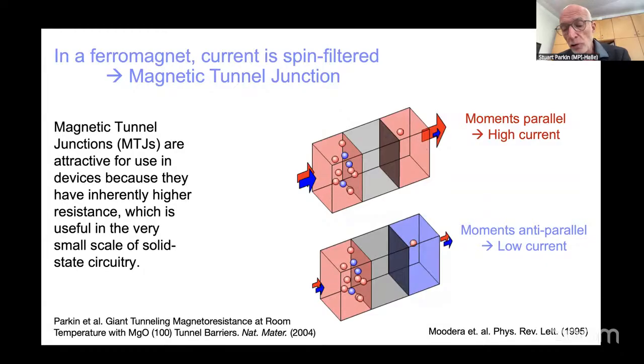What we showed in 2004, I showed that using a certain type of tunneling barrier, magnesium oxide, combined with body-centered cubic cobalt-iron electrodes, they have a very special characteristic: the spin up and spin down electronic states at the Fermi energy have very different electronic characters. The majority spin polarized electrons have extended sp-like states, and the minority electrons are more d-like. This means that the sp electrons are spin filtered by the tunneling barrier, leading to effectively a near 100% polarization of the electrons via spin filtering through a non-magnetic tunnel barrier. And this leads to giant tunneling magnetoresistance values at room temperature. We demonstrated, in 2004, actually in 2002, values of several 100%.